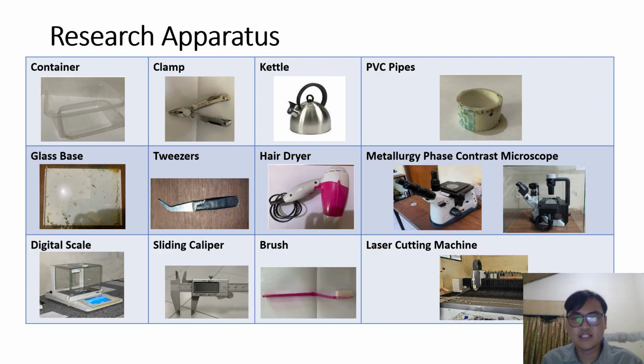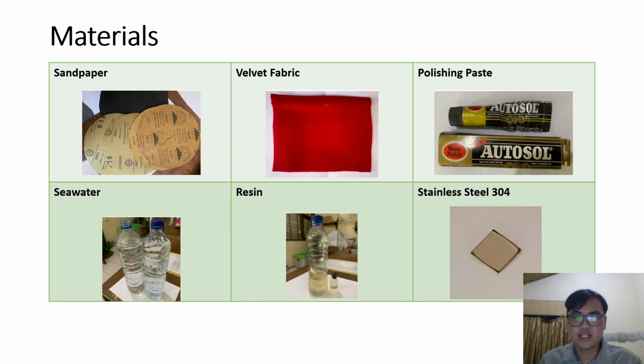We utilize standard precision equipment including digital scales, metallurgical microscopes for surface analysis, and a laser cutting machine to ensure precise specimen dimensions. The other apparatus were container, clamp, kettle to boil hot water, PVC pipes, and glass base to mount the resin, tweezers, hair dryer, sliding caliper to measure the dimensions, and brush for cleaning purposes. The primary materials used were stainless steel 304 plates, Jimbaran seawater, resin for mounting specimens, and polishing materials like sandpaper and velvet fabric for microscopic preparation.